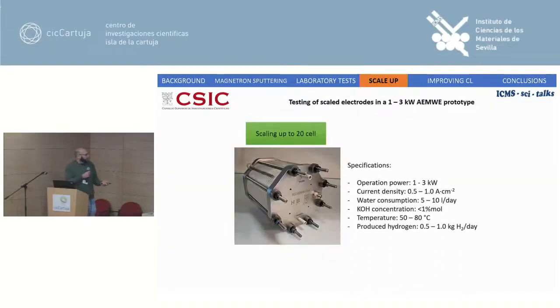Here I have grouped all the characteristics of this 20-cell stack. It can operate between 1 and 3 kilowatts of power at a current density between 0.5 and 1 ampere per square centimeter, and in this condition it is able to obtain between 0.5 and 1 kilogram of hydrogen per day.